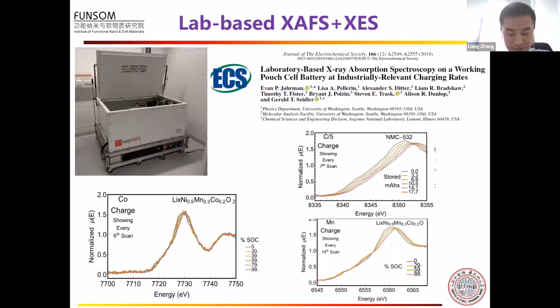In addition to the soft beamline, we also recently ordered a lab-based XAFS and XES. The energy range for the lab-based XAFS is between 5 keV and 12 keV. So this equipment can be used to measure the K-edge of the 3d metals, which is perfect for battery research. By using this equipment, we can also develop some in-situ operando cells to investigate the reaction mechanism of lithium and related batteries under real operation conditions. This paper published by Jerry used this lab-based XAFS to investigate the typical NMC electrode for lithium-ion batteries.